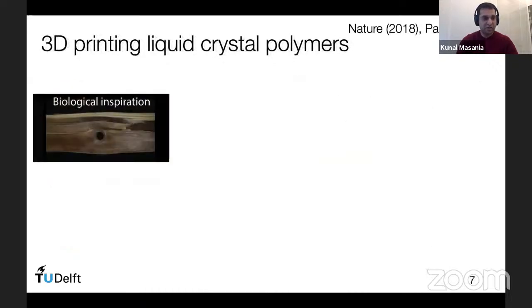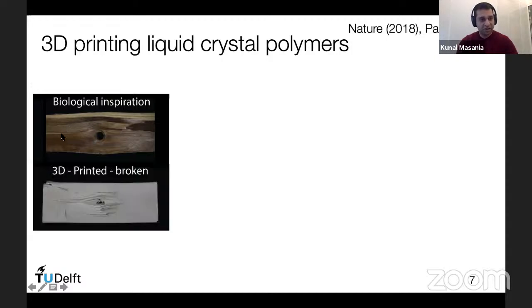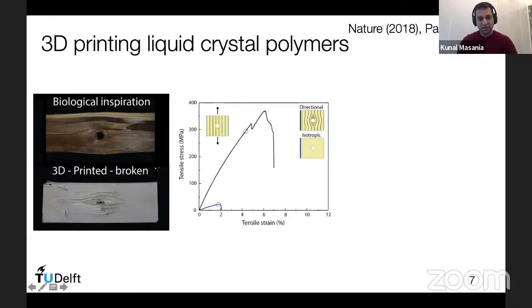And we can really utilize this shaping freedom that you can get from 3D printing. So here is an inspiration. So it's the example of wood. And what we can do is we can follow stress lines around the hole. But as you might know from other composite manufacturing technologies, you have to change the spacing of the lines locally, so you cannot fill with material. Whereas in our case, because we print a polymer, the polymer is self-assembling, and we have really building blocks at nanoscale. So we can easily change the density of our lines around holes. And what this means is we can go from something which is quite low in strength and stiffness from the isotropic material into something that becomes very, very stiff and very strong in the end. So we're talking about open hole strength of around 370 megapascal and stiffnesses of around 25 to 30 gigapascal.